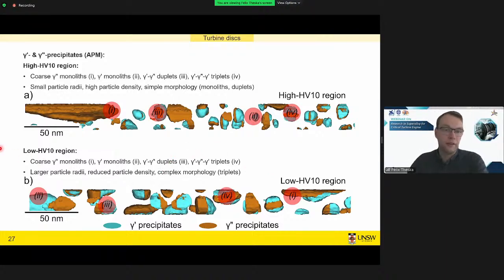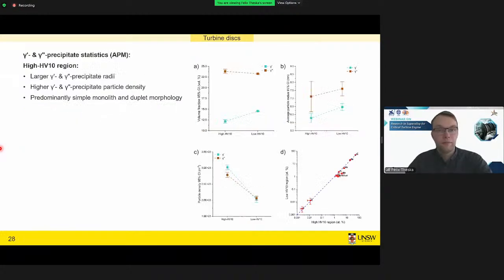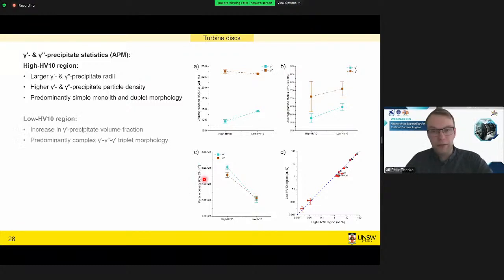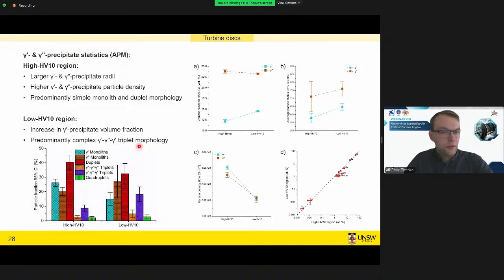And considering the particle size and density, these are very important indicators that could explain the lower strength. Now, if we compare these as plots, we find that the volume fraction and radius show small differences, but especially the particle density has a major change here. Okay, and here we have the plot of the different morphologies as a summary.